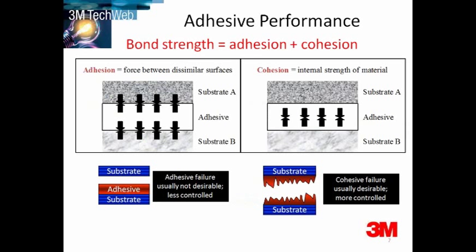The initial performance characteristics of an adhesive joint is governed by the adhesion and the cohesive strength. Adhesion is affected by the substrate characteristics, surface energy, surface preparation, and the adhesive type, chemistry, curing system, etc. Adhesion is defined as the ability to wet out substrates. It is affected by the surface energy of both the substrate and the adhesive, and the adhesive chemistry. Cohesion is the internal strength of the material and is affected by the adhesive type, cross-link density, modulus, and strength of the adhesive.